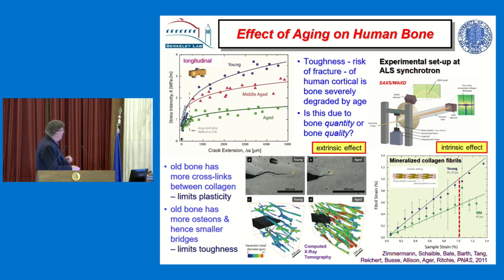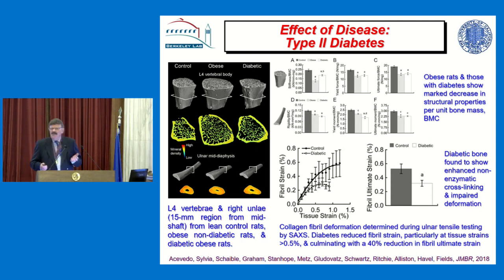Now, it turns out that a lot of these mechanisms play a big role in various diseases of bones. One of the top things is if you have aged bone, and if you have diabetes as well, that makes things much, much worse. Forget all the details here, but this is again looking at the strain in the collagen versus the strain in the tissue itself. You can see this is healthy bone, and we're quite high, but if you have diabetic bone, much less strain is carried by the collagen. And the reason is that diabetes, and I don't understand all the medical aspects, leads to a lot of cross-linking, which locks this deformation mechanism.